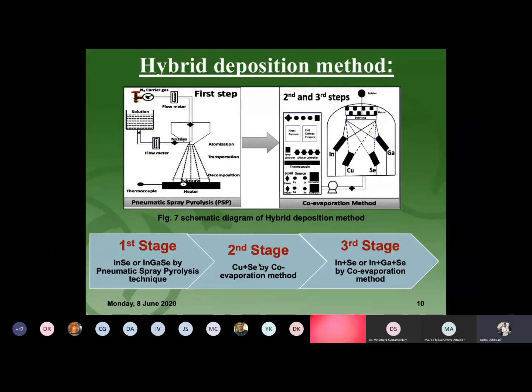The idea of this stage is to get the transition from copper-poor to copper-rich composition, which is called the recrystallization phenomenon, and this helps to increase the grain size by diffusing the group III elements into the liquid or pseudo-liquid phase, the copper-selenium phase.